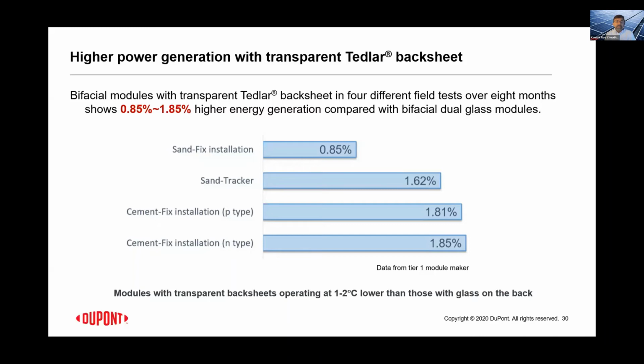What has been shown is that bifacial modules with transparent Tedlar backsheets in these 4 different field tests, well over 8 months, they are now producing in the range of about 0.9 to maybe 1.8, 1.9% higher energy compared with bifacial dual glass modules. Exactly the same BOM installed in exactly the same location. So it's a pretty good comparison in this case.